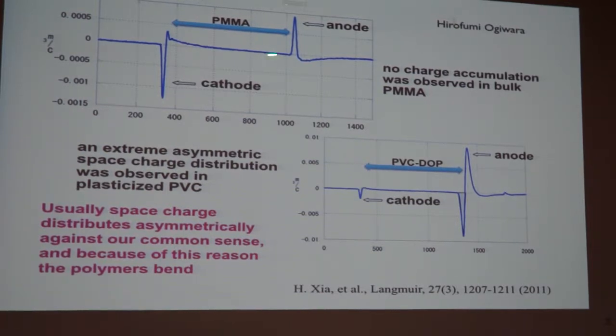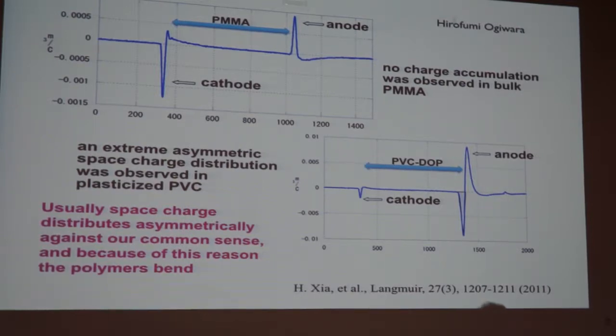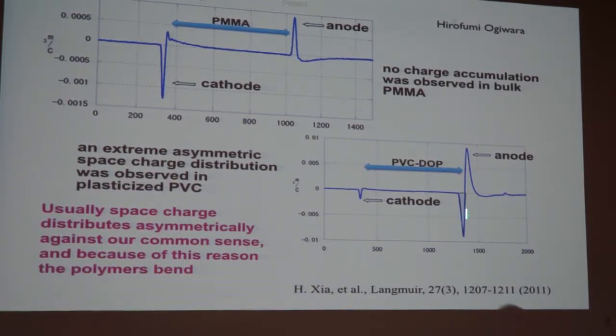The mechanism is proposed this way. PMMA is not an active solid field. And this is the anode, this is just a membrane. There is no charge accumulation observed. But in the case of plasticized PVC, on the anode surface, a large amount of negative charge accumulation was observed. On the cathode, nothing happens. This large difference, the asymmetry in the charge accumulation, causes that kind of deformation and that kind of activation in this case.